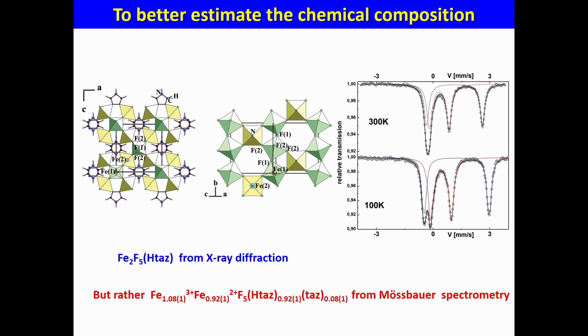Because the group has done some neutron diffraction, it is necessary to have a huge quantity of sample. For each batch I made spectra, and the results were systematically 53-47. Consequently, they were thinking that Mössbauer was right, of course. And it was possible to change the composition, which is given here. After, they considered such a composition for the X-ray pattern, and it was possible to see a small improvement of the fit. So it's a typical case where you can improve the composition of the sample.